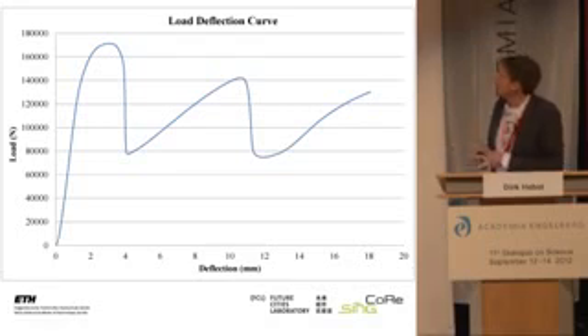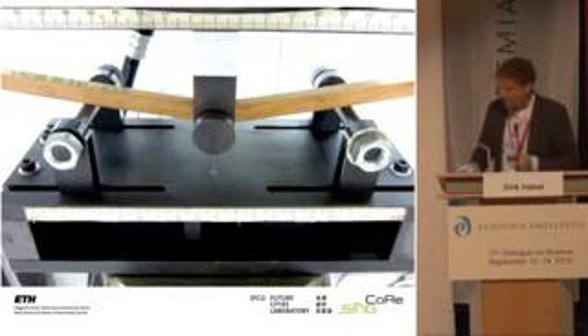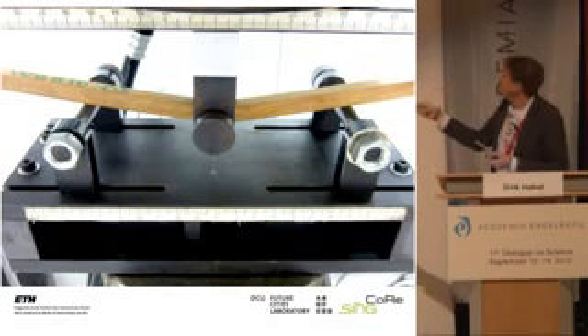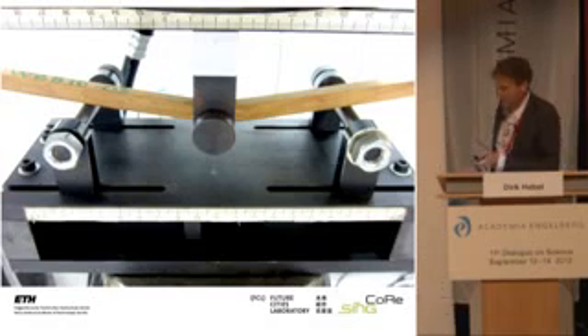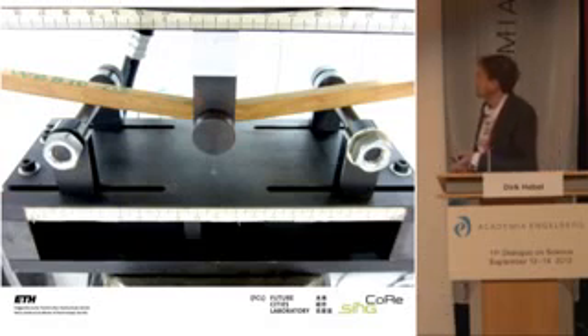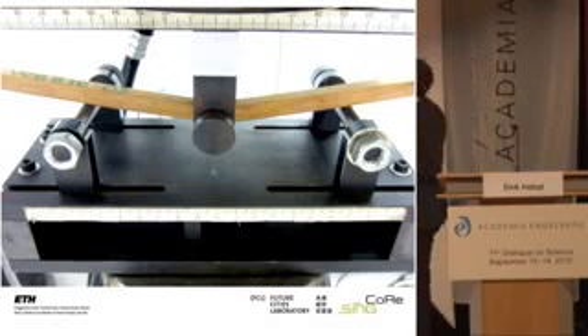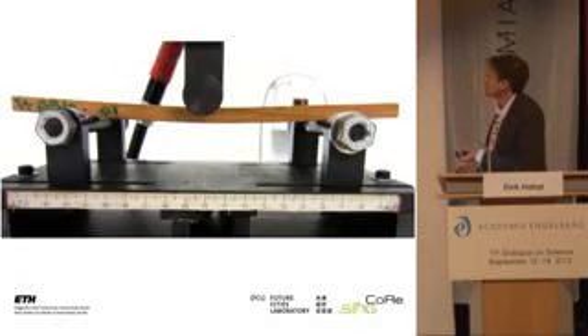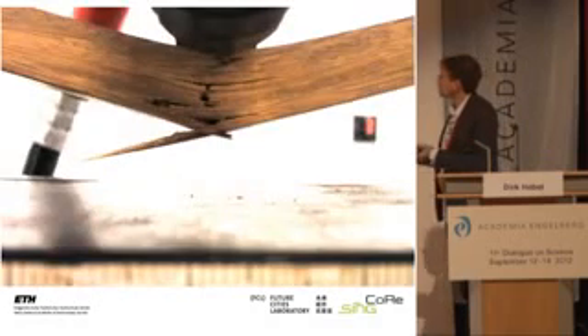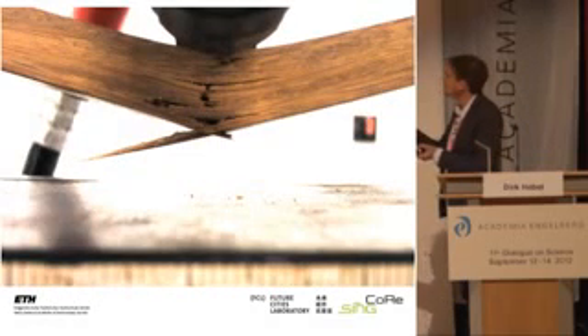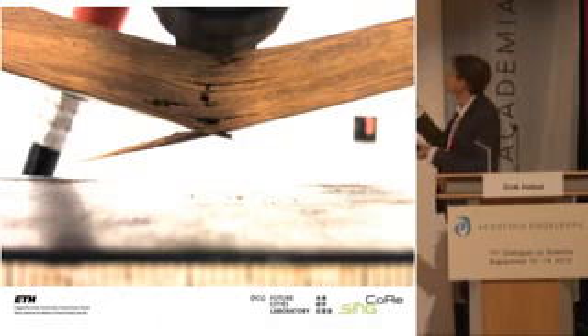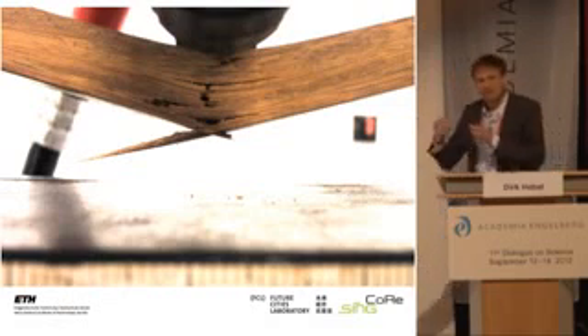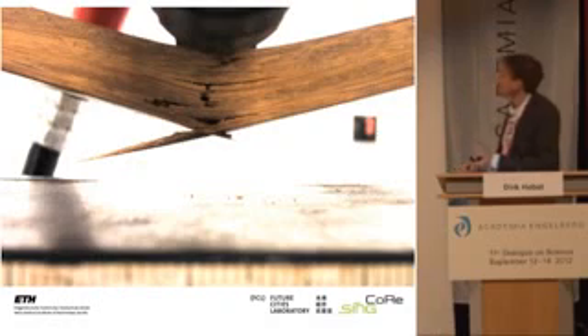We do bending tests. So basically you see here that is again a beam, a bamboo beam, and we press in the middle to understand what the bending capacities of that is. That's also an interesting fact that we realize in these tests, that we don't have problems with cracking, so it only appears on the lower end, but because the material is so flexible, the upper part of the beam is still intact, and remember the graph, that you can take still capacity, load capacity, even so the material is not failing in an instant.